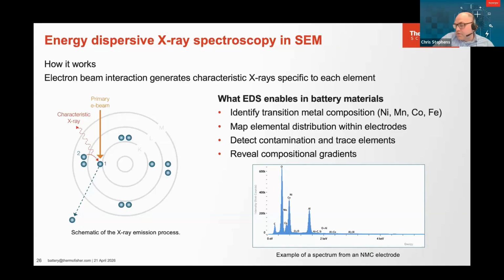So within the material itself, this matters because you then get the localized composition, so we can see precisely which elements are there. We can map these spatially, so we can see how that distribution will vary through, say, the electrode. We can look at the individual contaminants, and this can go down almost to trace level, but also we can see individual compositional gradients, and that'll also tell you additional things about how the material is performing.